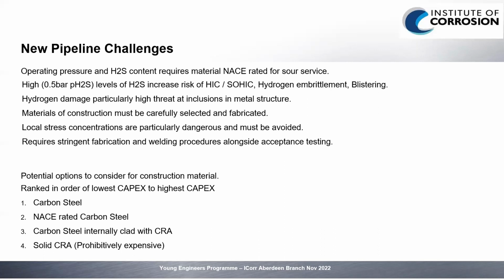So we've got particular areas where this would be a big problem. Could be inclusions in the metal if it's not sourced or manufactured properly, so we need to have a good selection of materials. Stress concentrations is another area. Any leftover residual stresses from forming, from manufacture, or from welding need to be really minimized to avoid these damage mechanisms. So the construction would be by a third party, but we would work with you to make sure that everything's being done as per procedure and everything's correct.